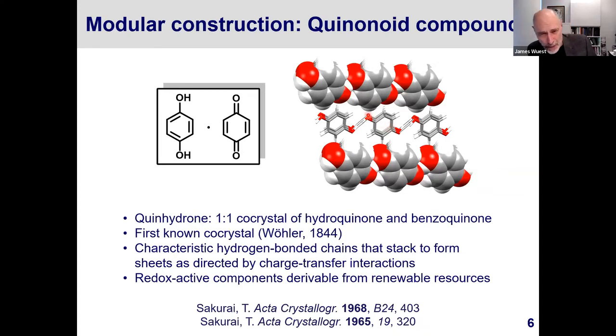Now, these compounds were characterized crystallographically, well, it's about 60 years ago almost, by Sakurai. The idea of using these as modules and controlling the structure by hydrogen bonding and charge transfer does not completely eliminate polymorphism, but as I said earlier, it minimizes polymorphism and makes sure that all of the polymorphs are structurally similar. So the polymorphs in this particular case, there are two of them, and they really differ in the way the planes, these layers, are arranged relative to one another.